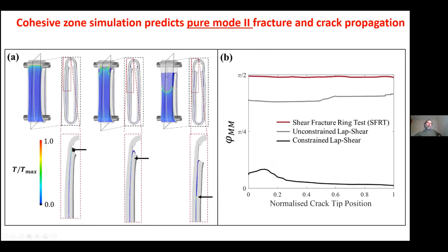Here's time zero. The crack is up here, and then it propagates. Instead of growing through the thickness, you can see the crack is growing along the artery. It looks like it's only grown a small bit from here to here, but in fact, it's grown all the way to here. It just doesn't look like a crack because the flap is only growing in shear. So the two sides of the crack stay in contact, but the traction is zero. So the crack has essentially grown as far as here. And our predicted mode angle here is pure mode 2. It's right on pi over 2.